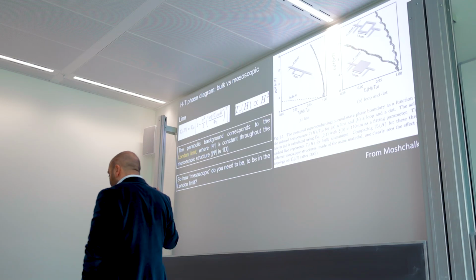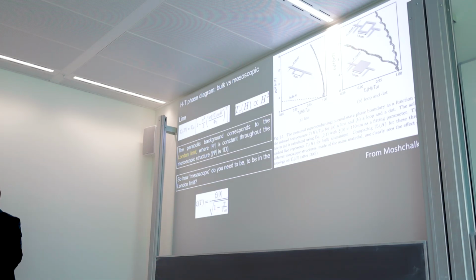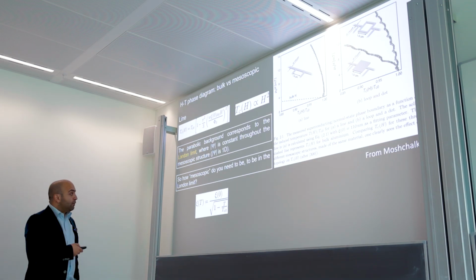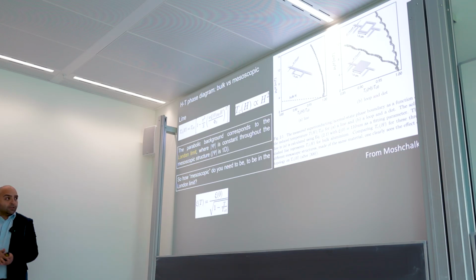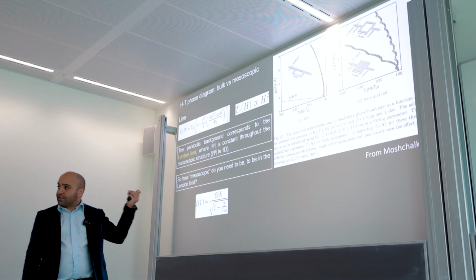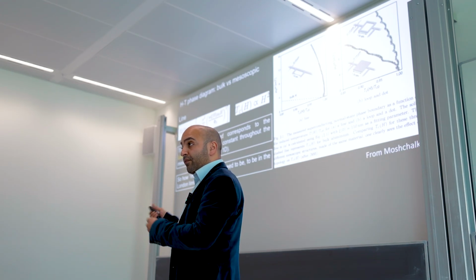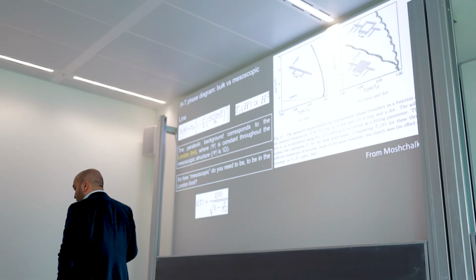But it is important to note that the coherence length, if you remember, is temperature dependent. You can see what happens when you go close to TC. Any idea what happens to the coherence length when you approach TC? Divergence, it shoots up. So even when your coherence length is, for instance, 10 nanometer, when you're close to the transition temperature it could be 100 nanometer. And then you will end up in the London limit. You end up in a regime where confinement effects kick in, and you have a higher critical field.